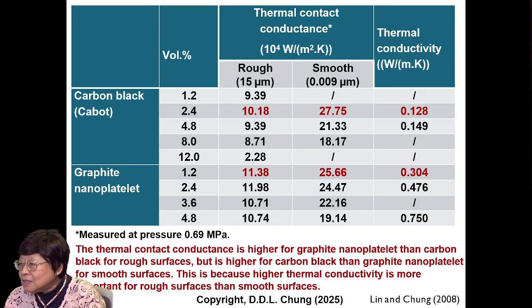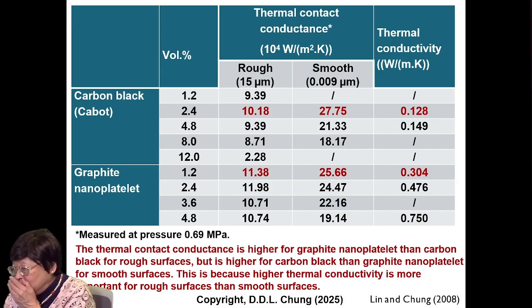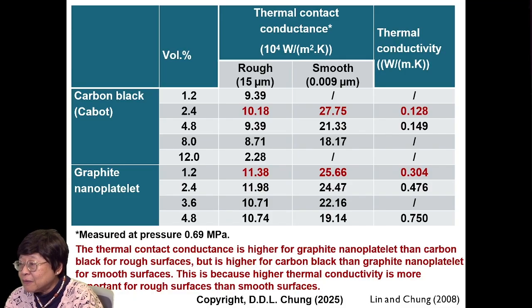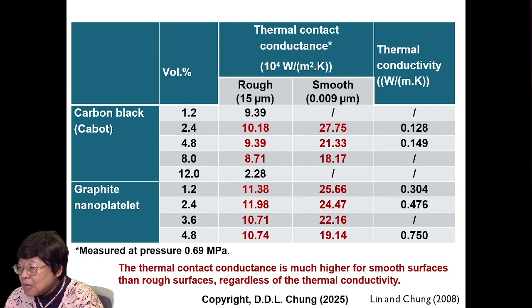The thermal contact conductance is higher for graphite nanoplatelet than carbon black for rough surfaces, but is higher for carbon black than graphite nanoplatelet for smooth surfaces. This is because higher thermal conductivity is more important for rough surfaces than smooth surfaces. And the graphite nanoplatelet has higher thermal conductivity than the carbon black case. The thermal contact conductance is much higher for smooth surfaces than rough surfaces, regardless of the thermal conductivity.